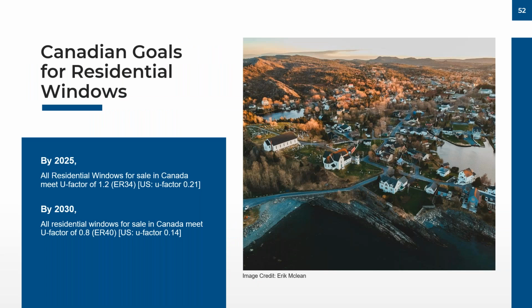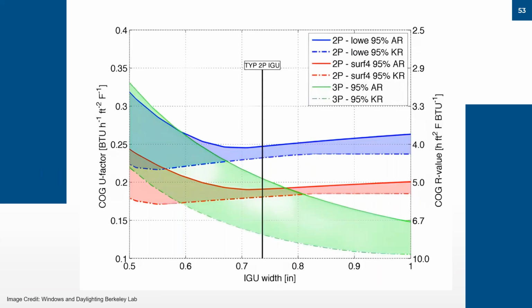Even if we look to our neighbors to the north in Canada, they have aspirational goals for residential windows starting just next year, in a couple months, that all residential windows will need to perform to a U factor of 0.21. That's an advancement from where they are now. And then in just 5 short years, that makes a big jump all the way up to 0.14 for the windows. So those earlier charts that we saw for overall glazing to wall ratio showed higher performing window systems, and that's the direction that certainly Canada is moving towards. So we have a need for higher performing windows than what a lot of the market has today.